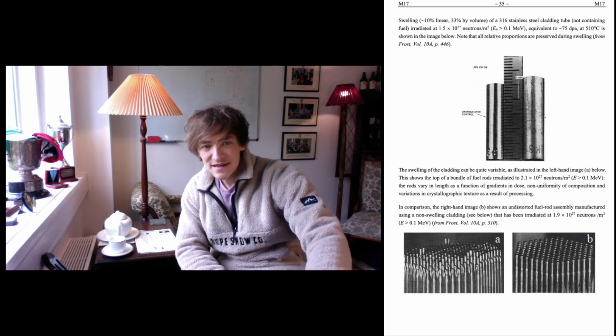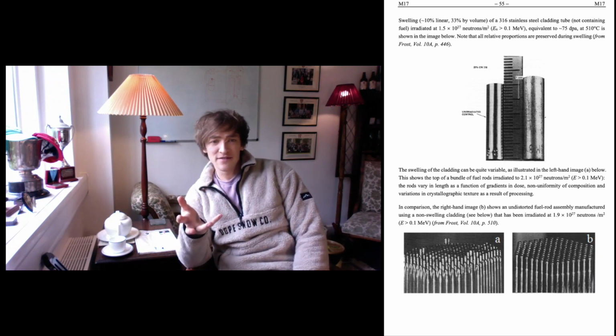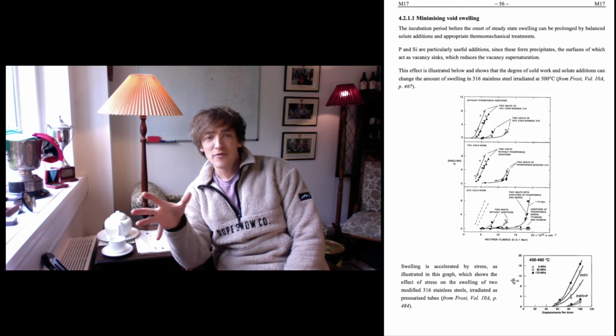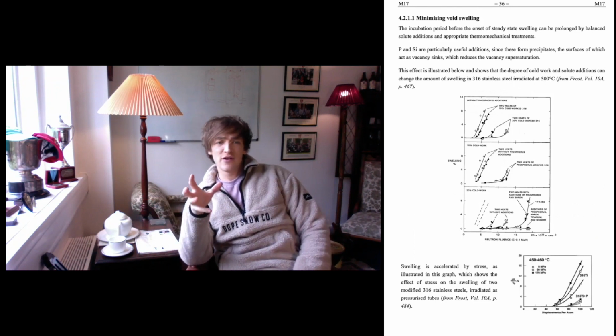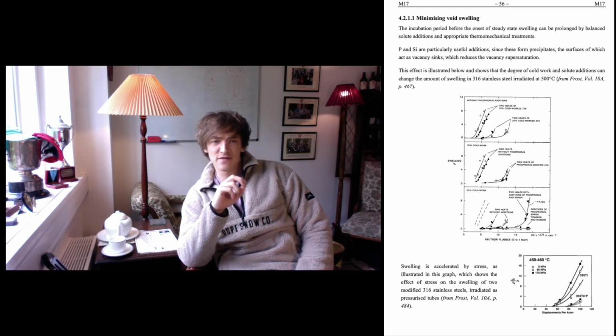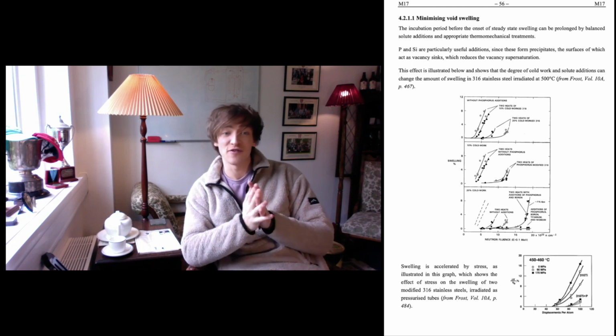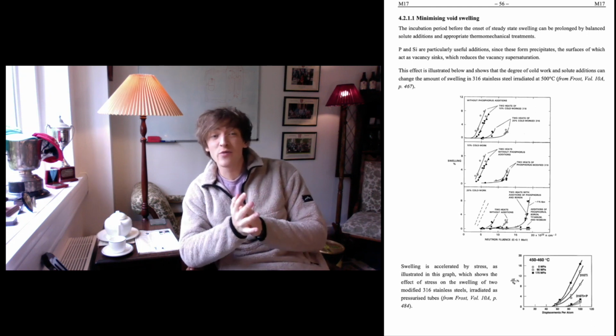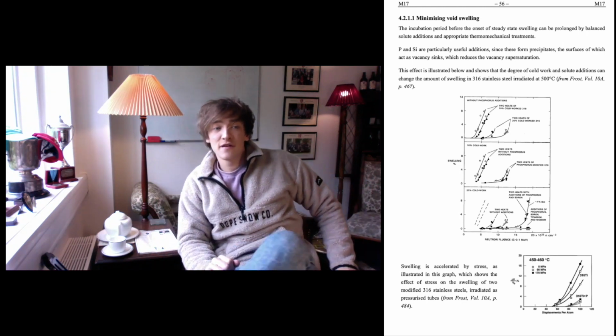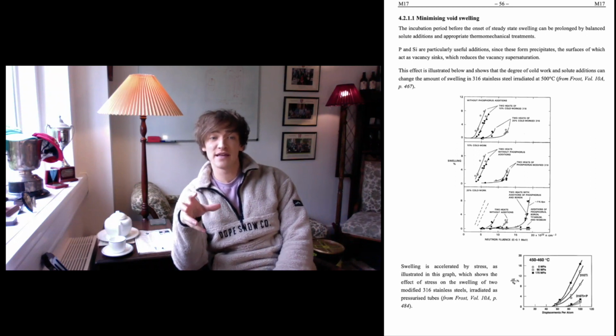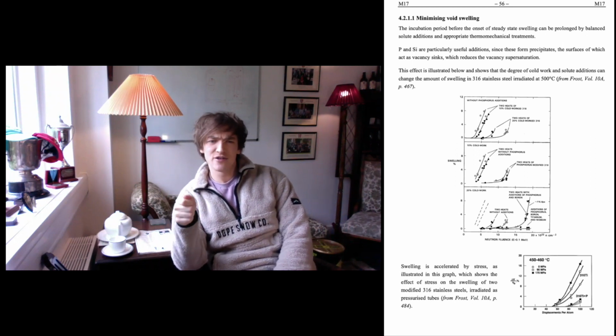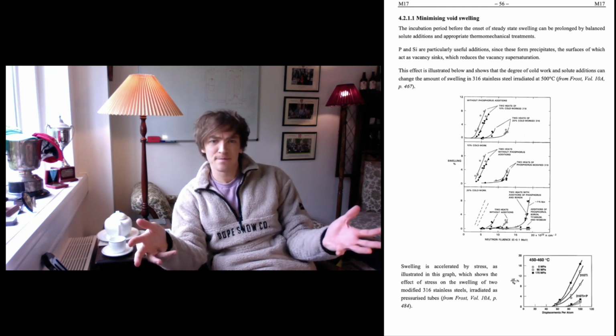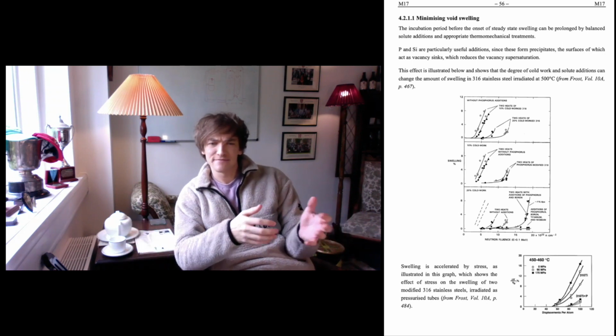Okay, so what does swelling resistant cladding look like? I mentioned it before. Well, for 316 stainless steel, if you look at the graph in the center of this page, page 56, you see the effects of cold working and also the additions of phosphorus among other elements. The reason why they add phosphorus to get this swelling resistant cladding is because it forms precipitates. And similar to the way that voids like to form, the surfaces of these precipitates act as sinks for vacancies. That reduces the vacancy supersaturation, which limits swelling. So you've got a more swelling resistant cladding.